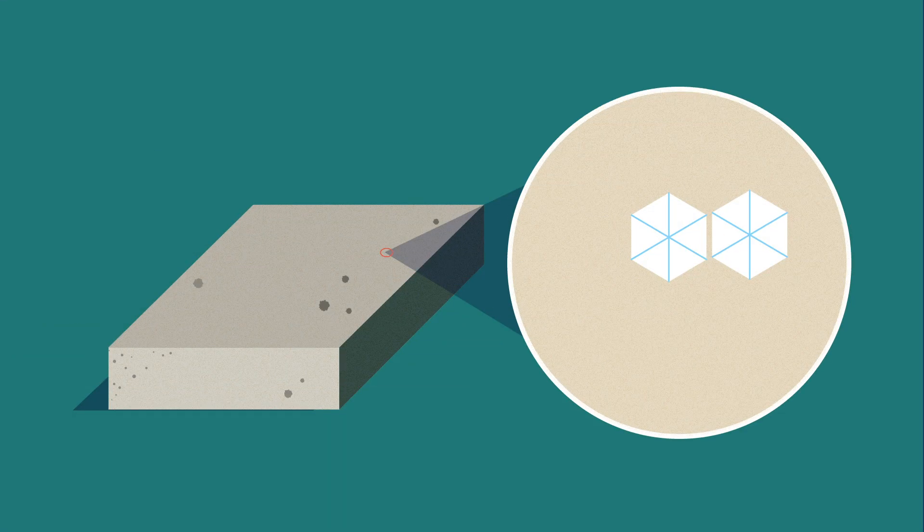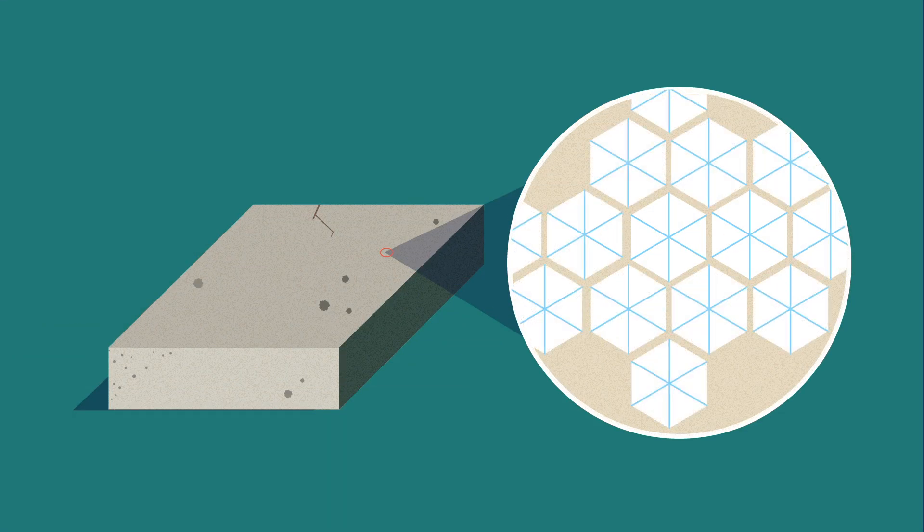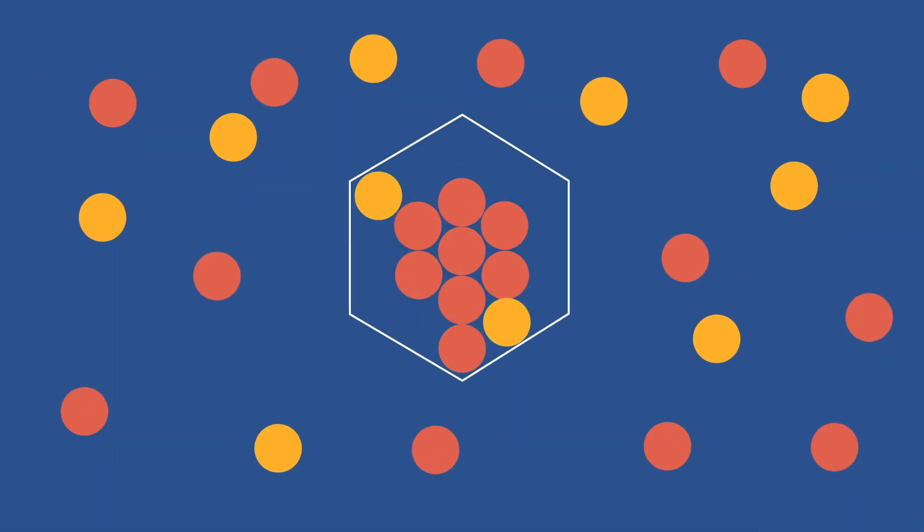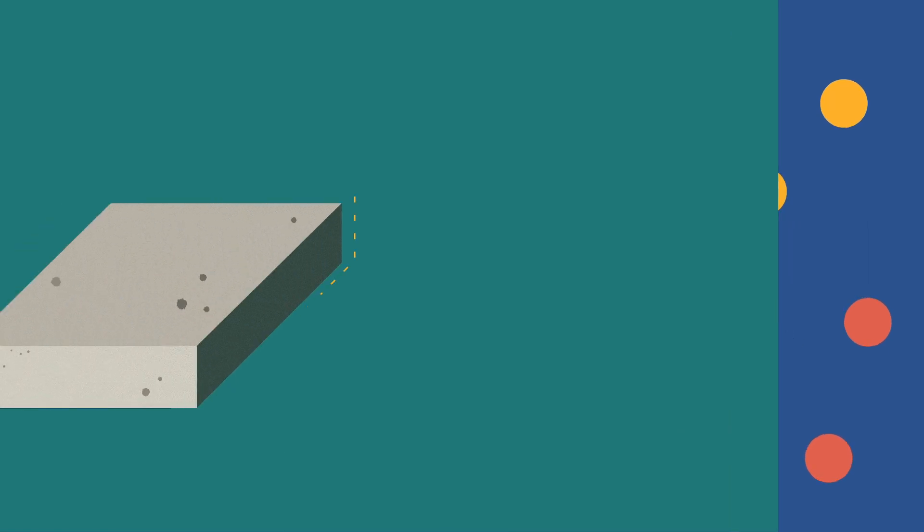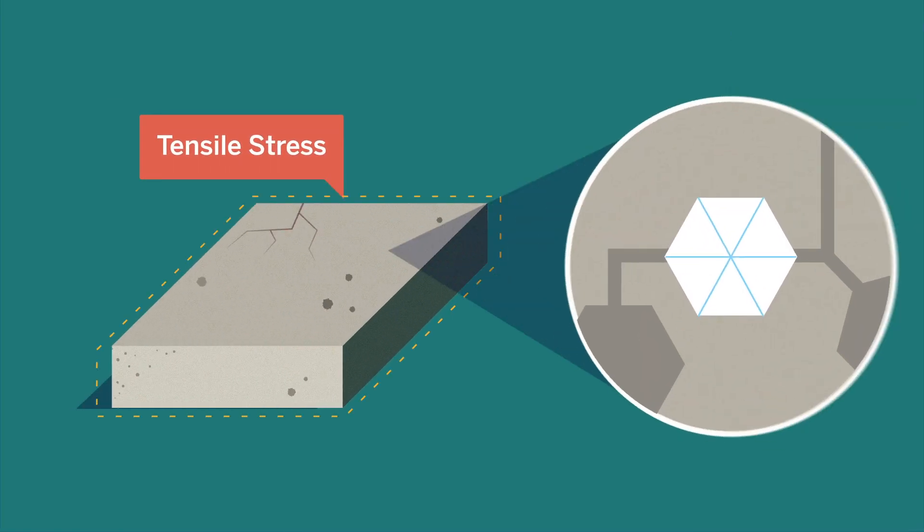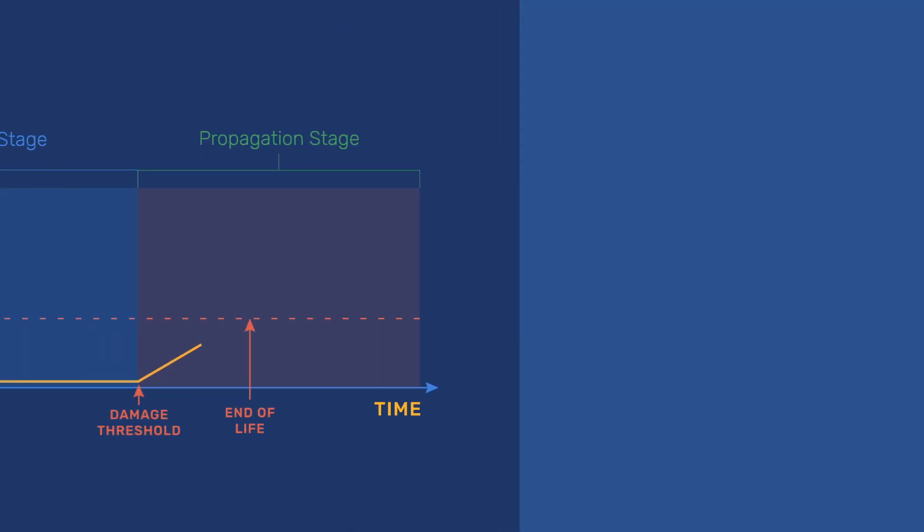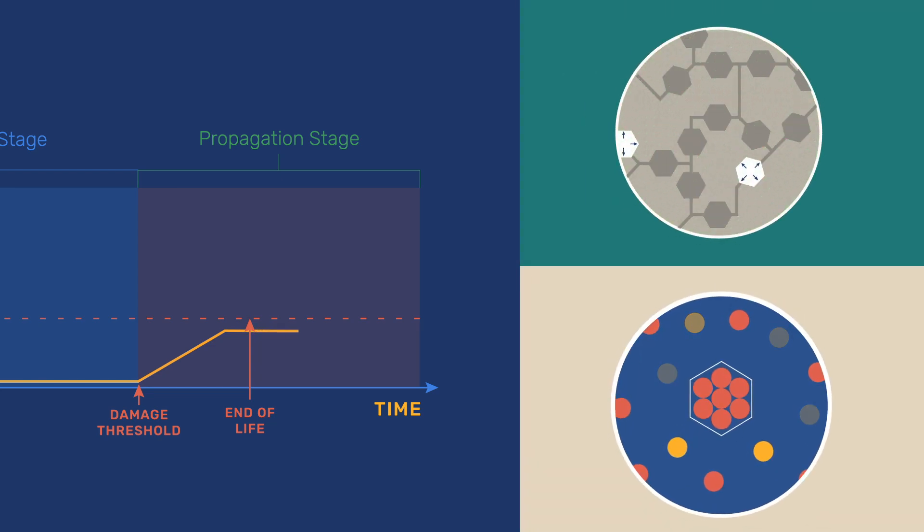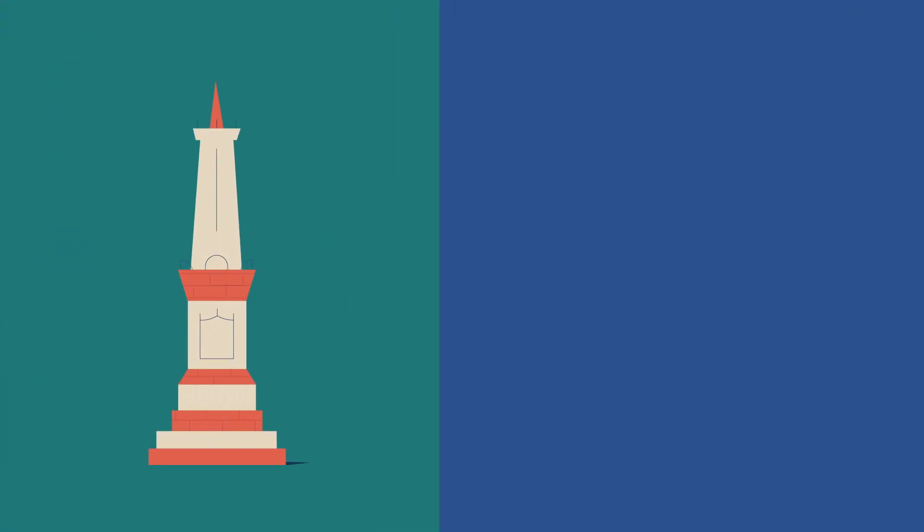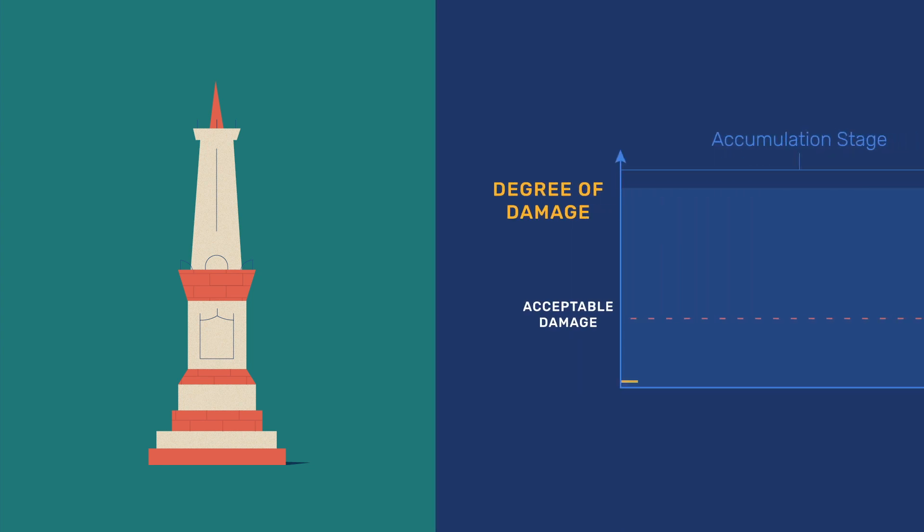In conclusion, the growth of salt in porous materials can be damaging when this occurs under conditions of sufficient supersaturation. For a given supersaturation, damage increases with the amount of salts exerting pressure on the host material, and with a decreasing tensile strength of the material. For conservation interventions, in the damage propagation stage, salt removal and reduction of supersaturation would be valid interventions. When replacing masonry elements by new stones, delaying the transport of salt should be the key concern when selecting those materials.